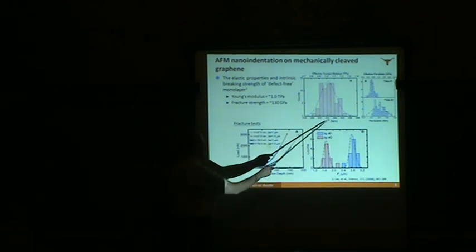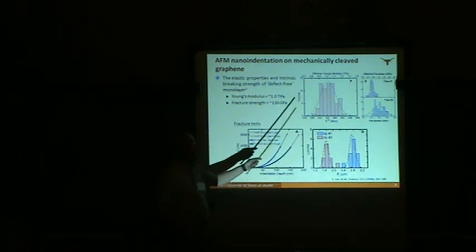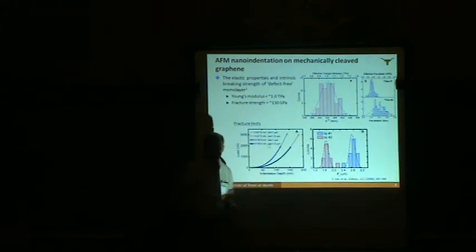And this shows the values of each mean parameter, which had a mean value around 1.0 TPa, just at the Young's modulus that we would have expected for the graphene. You can see the pre-stress values are pretty high, some as high as 1 GPa. The authors point out that pre-stress in the film exceeds the strength of many typical materials.